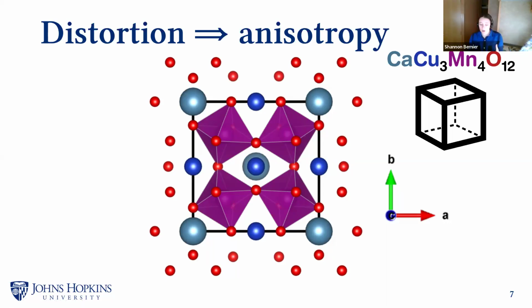And I bring this up in part because our method is very similar to previous ones where people have really carefully analyzed these coordination polyhedra, but we're actually focused a little bit more on the unit cell, as I'll mention more in a bit. But for now, the reason we might care about how far apart all these oxygens are is if there were a reason to expect that one of them was going to leave the structure when we reduced it. We knew it was going to happen to one of the manganeses, but we didn't know which oxygen it would be. When they're all symmetrical like this, they all have the same electrostatic interaction, and there's no real reason why it ought to be one versus the other.